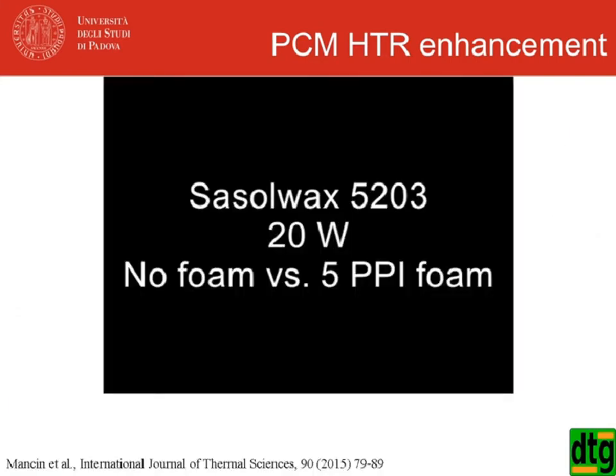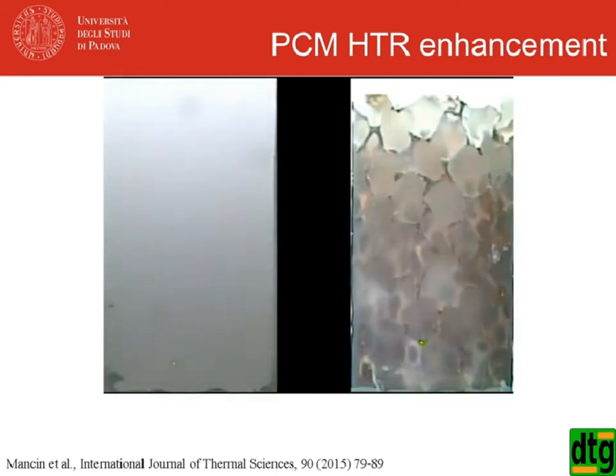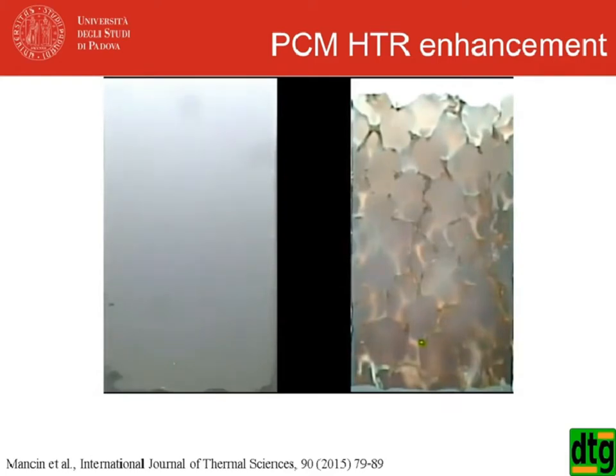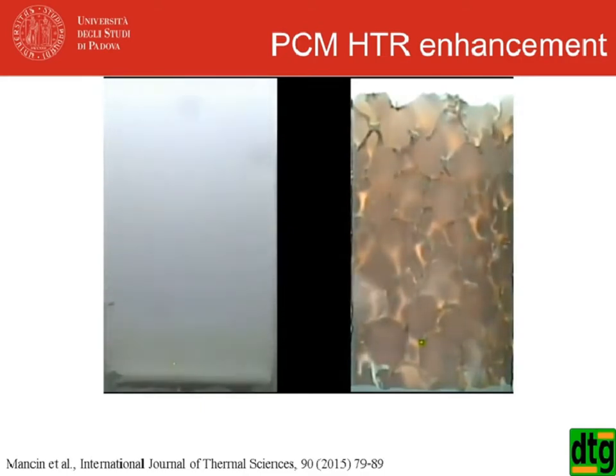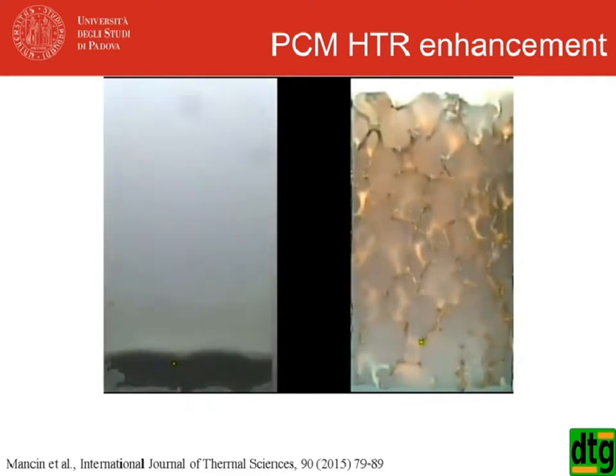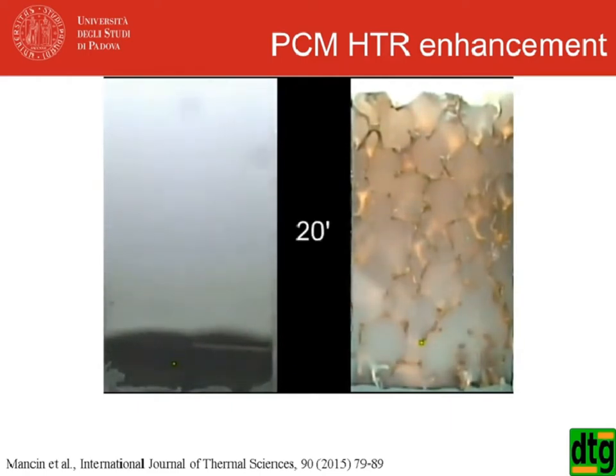So let's start with this. Okay, I want to show you just one video as a result of this. This compares the empty box, so without foam, with a 5 pores per inch foam at an imposed heat flux of 20 watts from the bottom. So as you can see, nothing happened at the very beginning for 10 minutes, but after 10 minutes, you see that on the left, the empty box, the melting process started, while on the other side, we just see that the volumes, or the wall, if you want, became a little bit brighter.